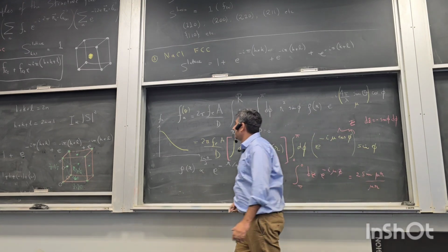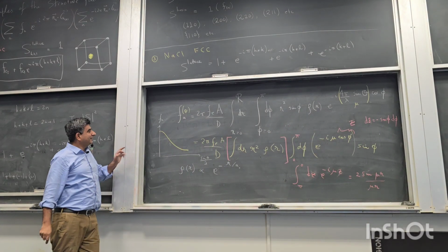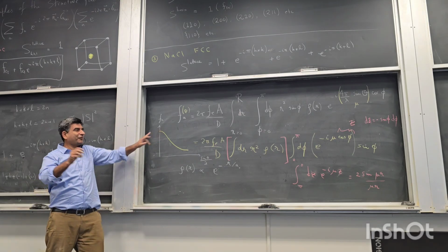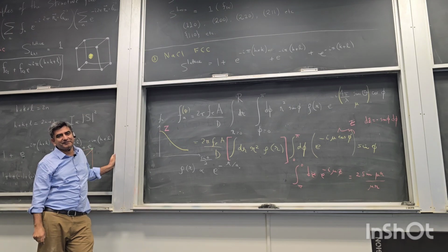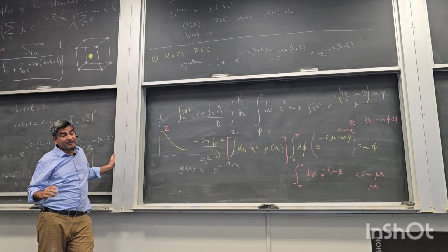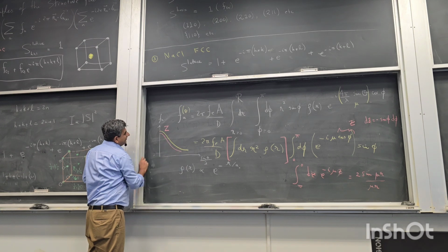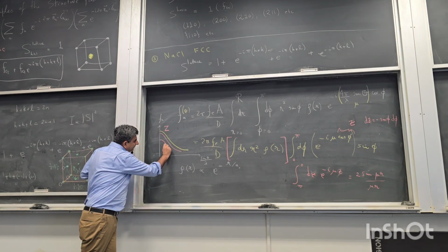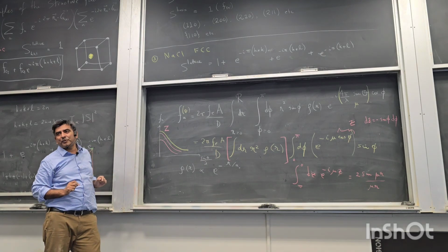So if I take aluminium at theta equals 0, it will start off from the atomic number of aluminium, 13. Magnesium will start from 12. Magnesium will have a curve like this. Carbon may have a curve like this. So they all start off from the atomic numbers.